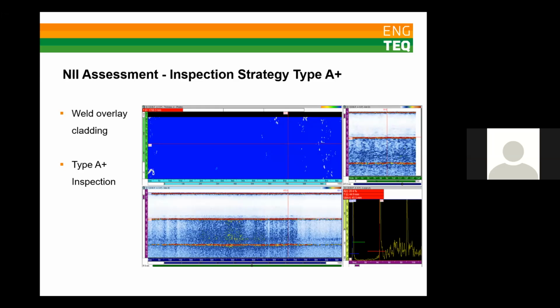So if the conditions are right, there is a possibility of cracks from the cladding progressing through the interface into the carbon steel, or under cyclic loading conditions by fatigue, but this is probably less likely. If corrosive fluids reach the interface due to cracking or any other local failure of cladding, then this would lead to corrosion of the carbon steel starting at the interface.